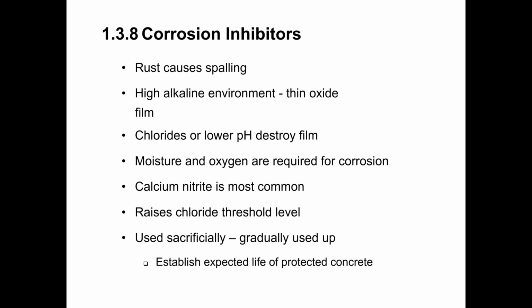Over time, the pH of the concrete environment goes down. It goes down naturally. It definitely is reduced in the presence of chlorides, such that we lose that protective thin oxide film on the reinforcing, and so the reinforcing becomes more susceptible to corrosion. In order to have corrosion, we need moisture and oxygen. So if we can keep moisture and oxygen off of the surface of the reinforcing, then that's going to go a long way towards minimizing corrosion. But since that corrosion wants to occupy more volume, it causes internal stresses in the concrete, ultimately leads to cracking and spalling, which then opens up the reinforcing to higher levels of moisture and oxygen, thus accelerating the corrosion process.